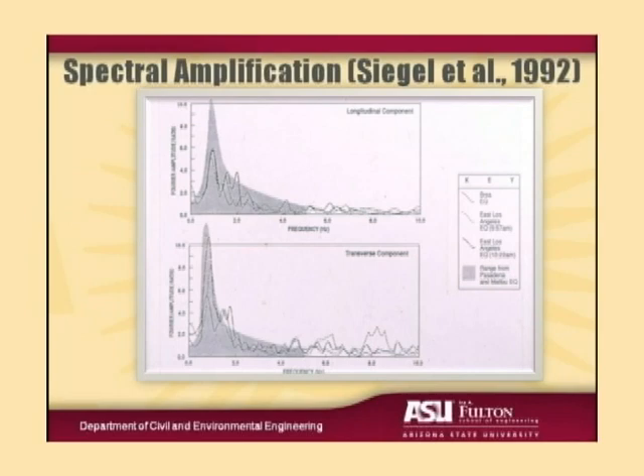Here you see spectral amplification on the order of 10 or 11 at about 1 second. That 1 second represents the natural period of the waste mass. In fact, if you take the average shear wave velocity from Professor Stokey's soundings and you pop it into one of my favorite formulas, that the natural period is 4 times the height of the landfill divided by the shear wave velocity, you come out with exactly 1 second. So this was some work done by CH2M Hill, but this work assumed that the base station was on bedrock.